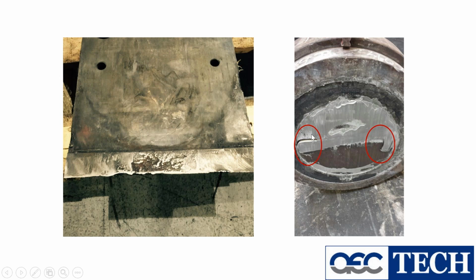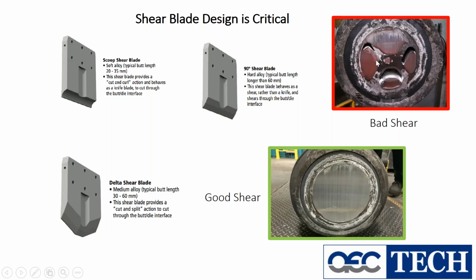So again, here's another picture where metal is being pulled out. This is not die design. This is not alloy. This isn't anything other than procedure. Again, we see a poor shear and we see a good shear. All shear blades are not considered equal. You should not use the same type of shear blade for super soft alloys as you would for hard alloys. A 6063 butt in 9-inch is a different size than a 6061 butt in 9-inch. So you can't expect the shear blade to shear it off and not pull metal out of the die.